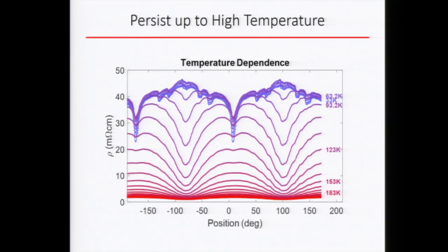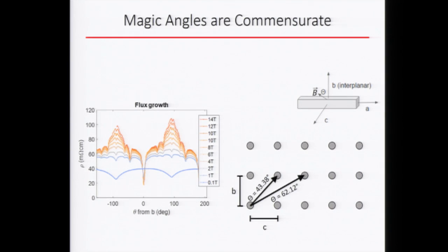And it actually persists to a rather high temperature. You can observe this all the way up to, let's say, 90 Kelvin for the first major peak around 0 degrees. And what are these angles? It turns out that these angles are 43.38 degrees and 62 degrees, and they actually correspond to the real space lattice vectors for the B and C direction. Whenever you rotate the magnetic field and hit the next unit cell, you see a peak.